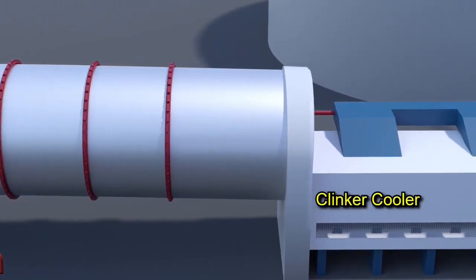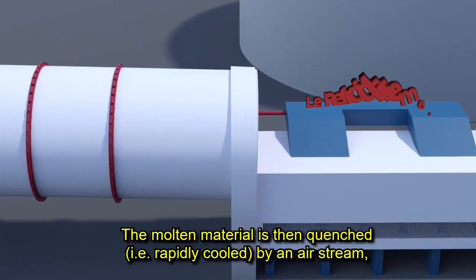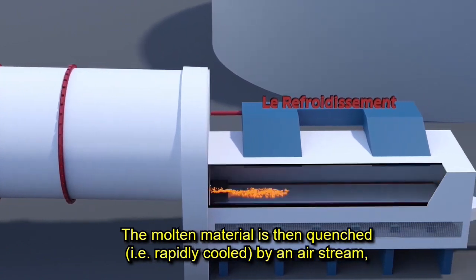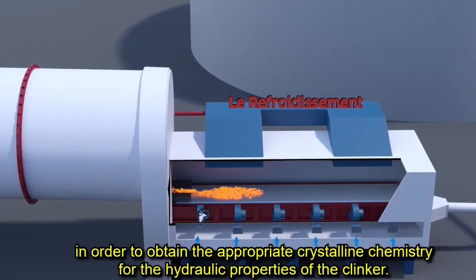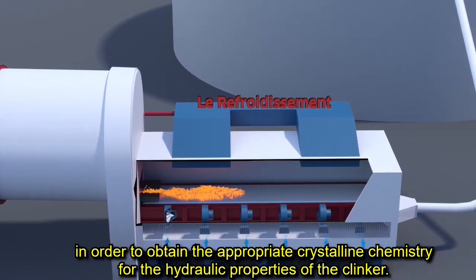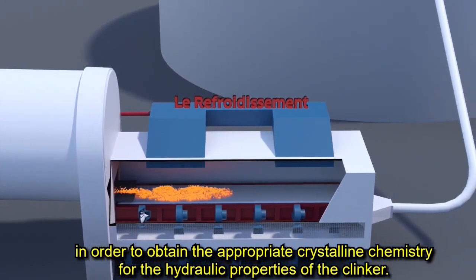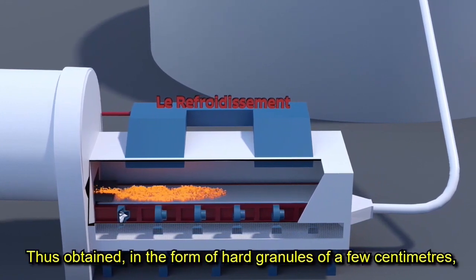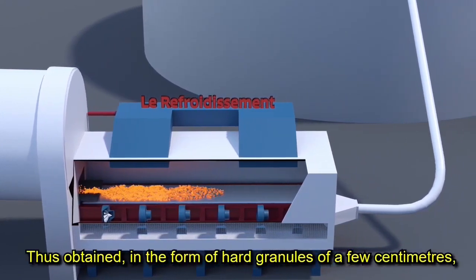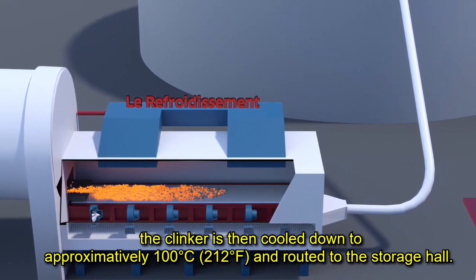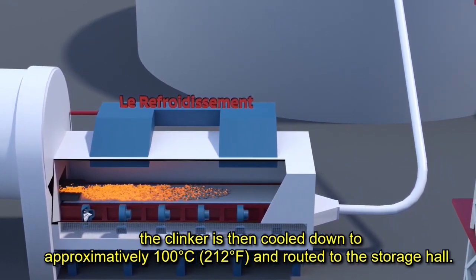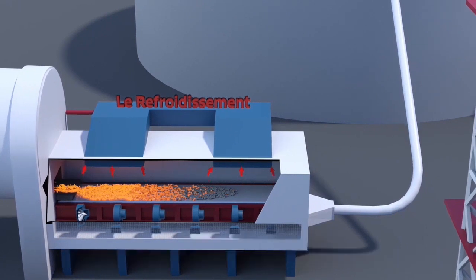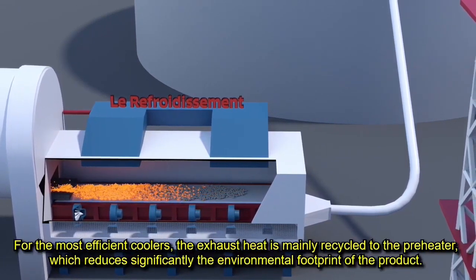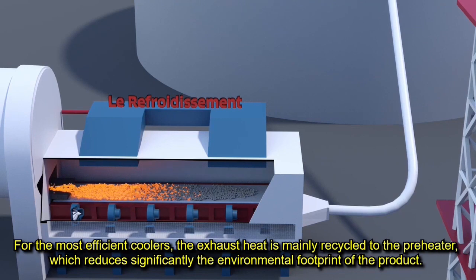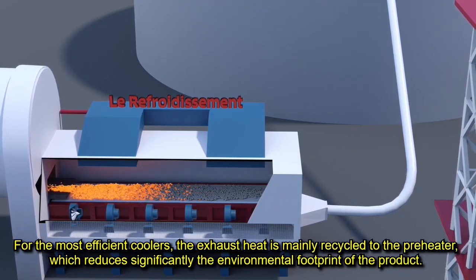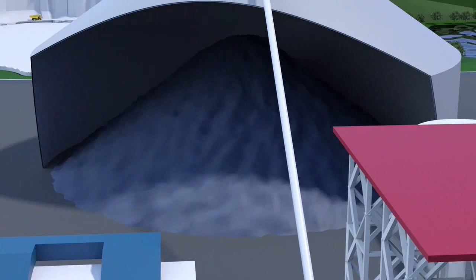Cooler. The molten material is then quenched, meaning rapidly cooled, by an airstream in order to obtain the appropriate crystalline chemistry for the hydraulic properties of the clinker. Thus obtained, in the form of hard granules of a few centimeters, the clinker is then cooled down to approximately 100 degrees Celsius and routed to the clinker storage hall. For the most efficient coolers, the exhaust heat is mainly recycled to the preheater, which reduces significantly the environmental footprint of the product.